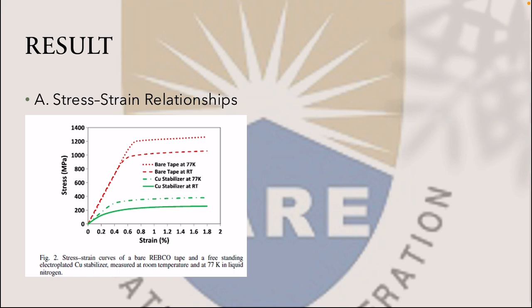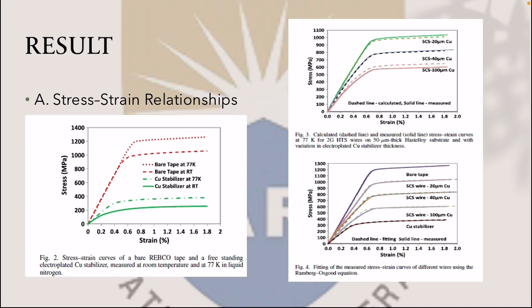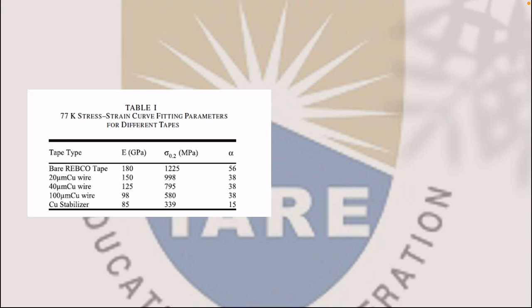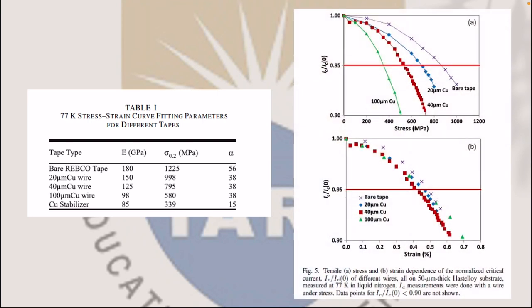Results: stress strain relationship. Figure 2 discusses the stress strain curves of a bare REBCO tape and the freestanding electroplated copper stabilizer. Figure 3 describes the calculated and measured stress strain curve at 77 Kelvin for 2G HTS wire. Figure 4 describes the fitting of the measured stress strain curves of different wires using the Ramberg-Osgood equation. Table 1 describes the 77 Kelvin stress strain curve fitting parameters for different tapes. And Figure 5 describes the tensile stress and strain dependence of the normalized critical current.